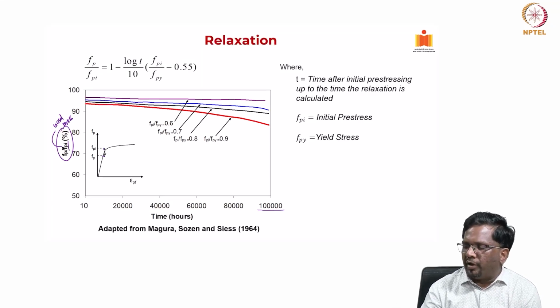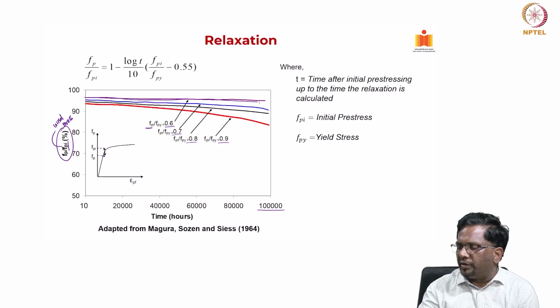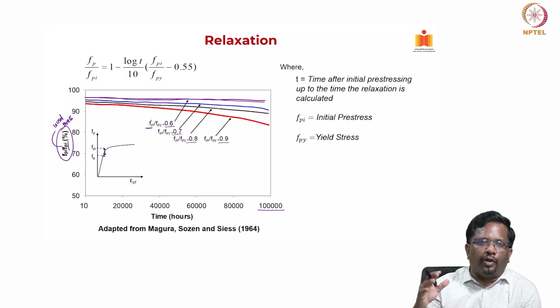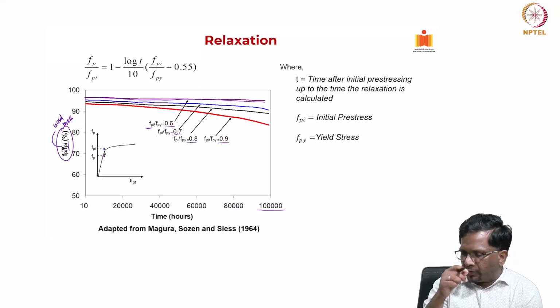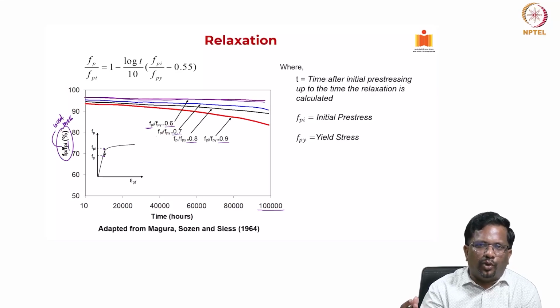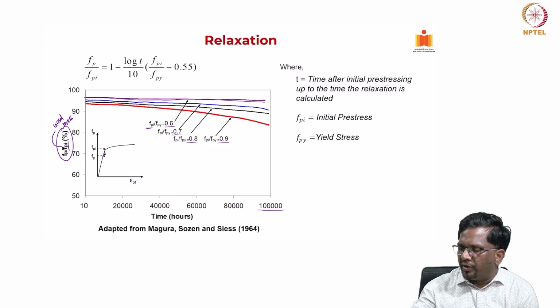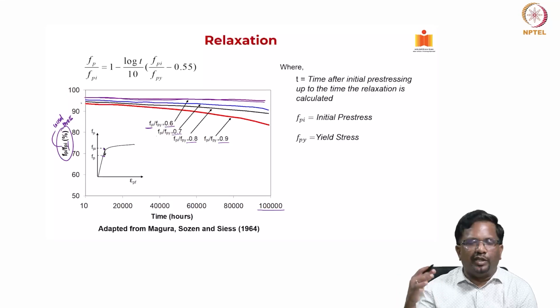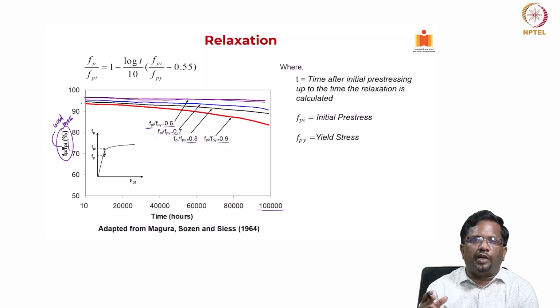Now, you can plot depending upon how much my initial stress is, whether it is 60% of the yield strength or 70% or 80% or 90% of the yield strength. So, what you see here, if I keep the initial stress as 60% of your yield strength, I get this curve, right. This is a nice curve that you get. And if my initial stress is kept much lower than the yield strength, what you find here is this is the original ratio. If this ratio is close to 100, that means there is no loss, right, there is no loss. So, you can see for the violet color, when the initial stress is about 60%, even at 100,000 hours the actual stress remained at about 95 to 96% of your initial stress. That means that relaxation loss is less when FPI by FPY is small.